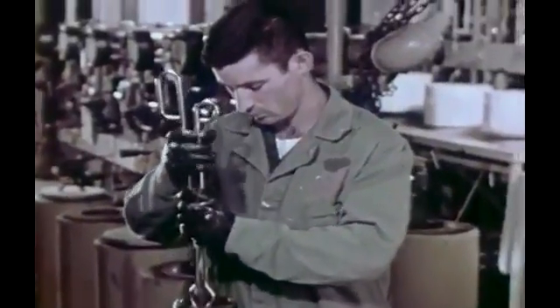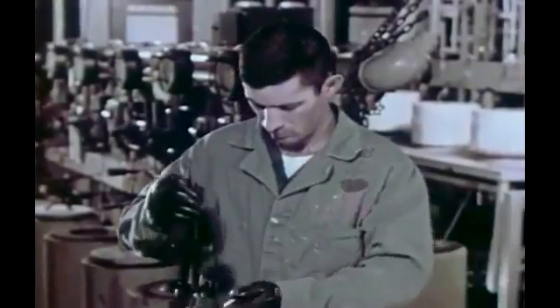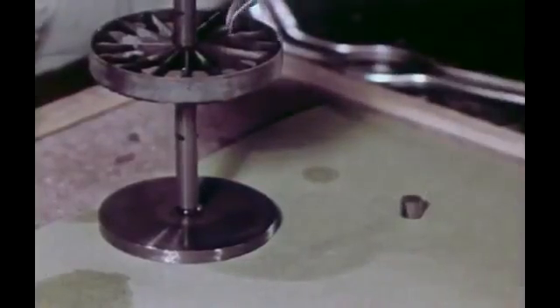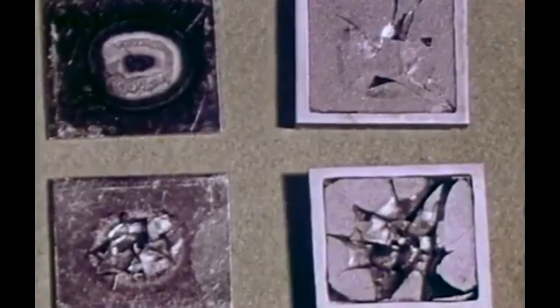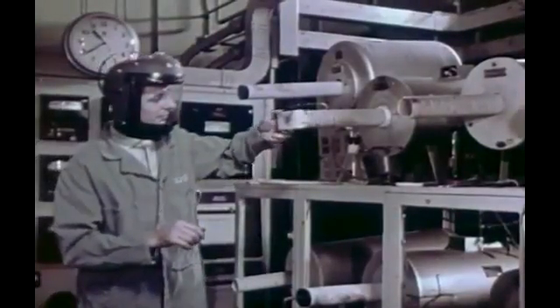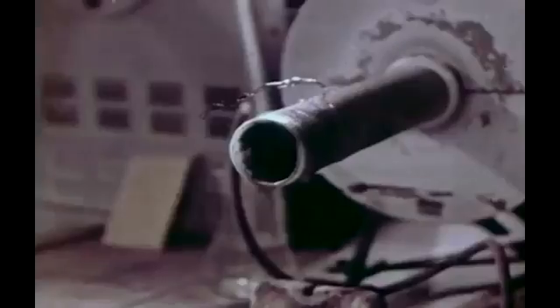Many aspects of the chemical behavior of the oxide were studied. These included such things as its reaction with hot water, its reaction with a zirconium alloy, which might be used as cladding, and the effects of particle sizes on chemical behavior. It was found that UO2 could be sintered successfully if carried out in a hydrogen atmosphere.